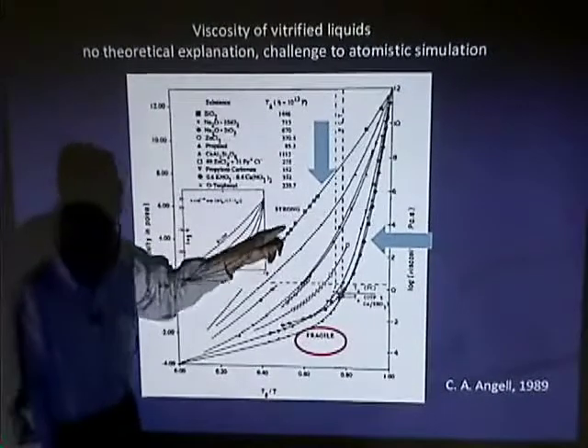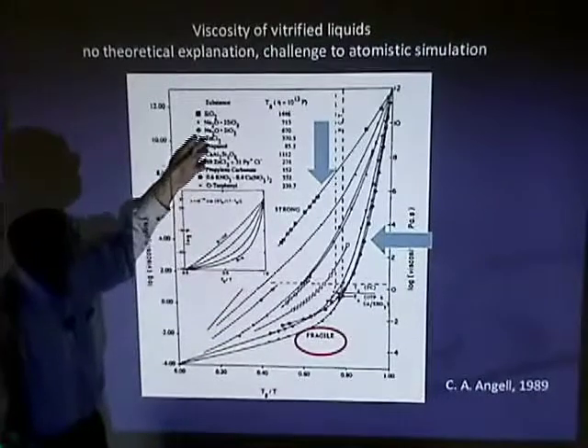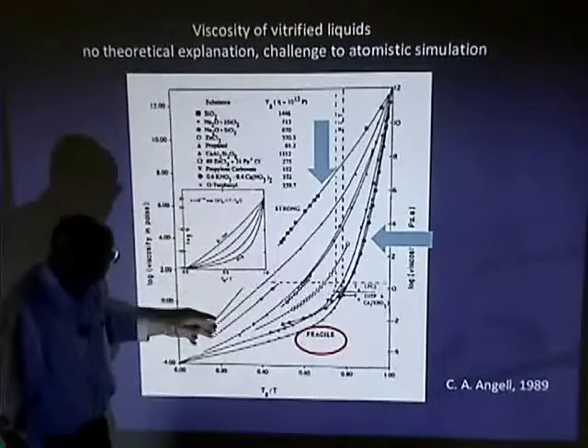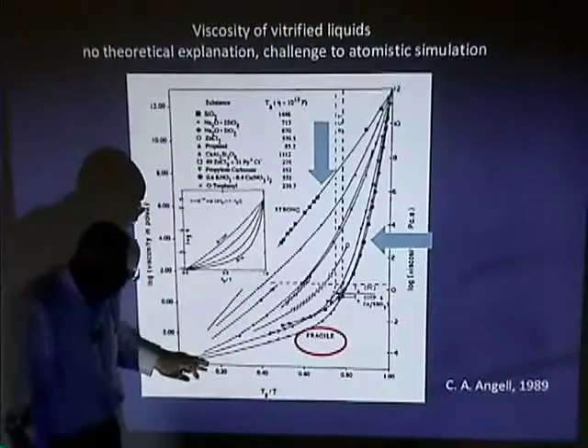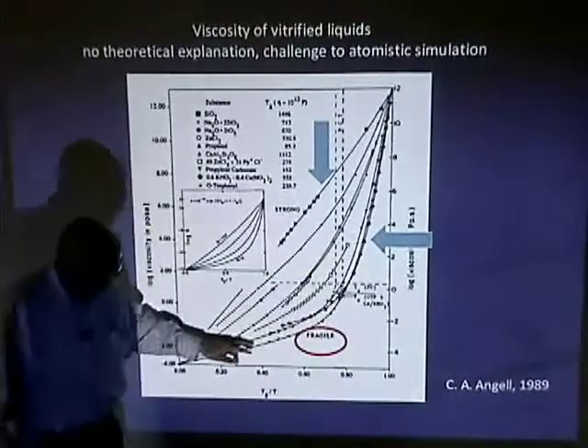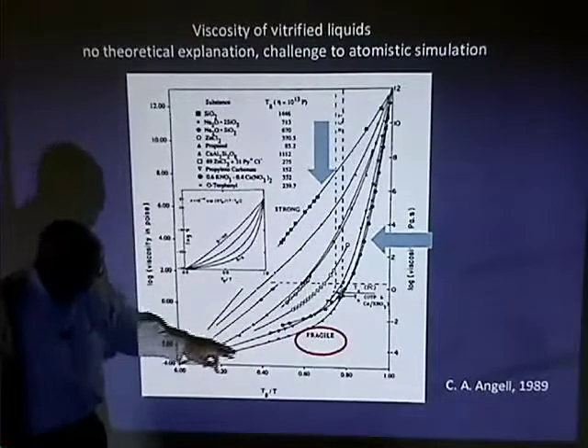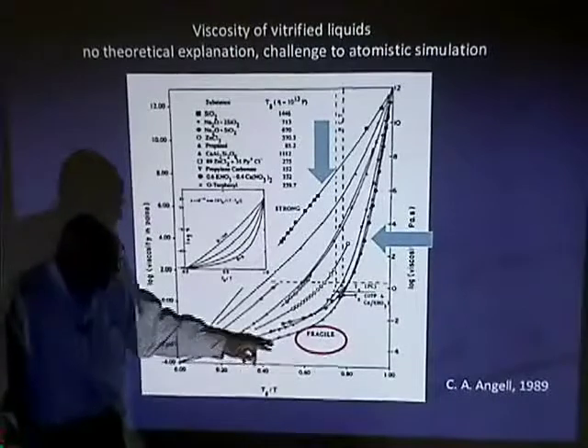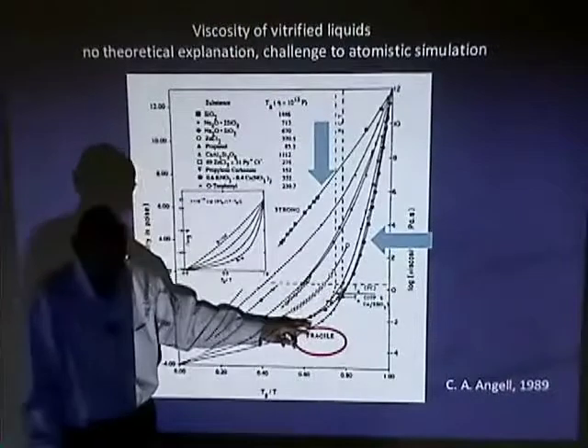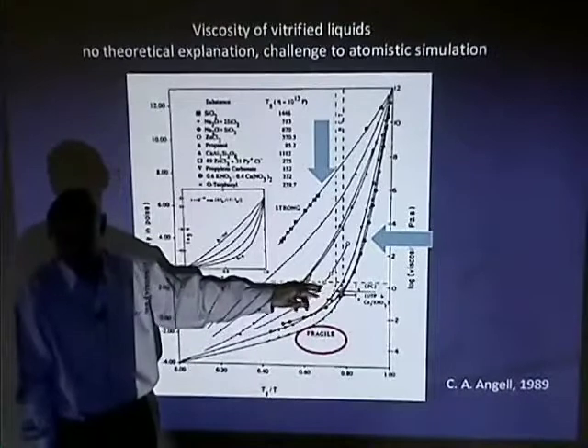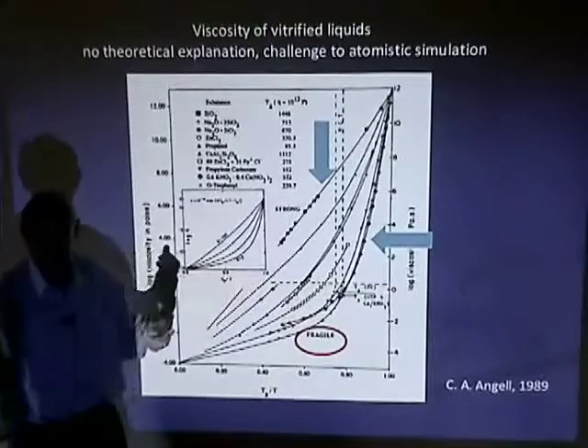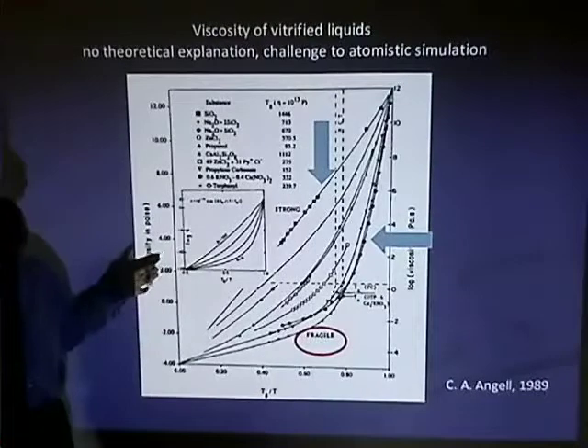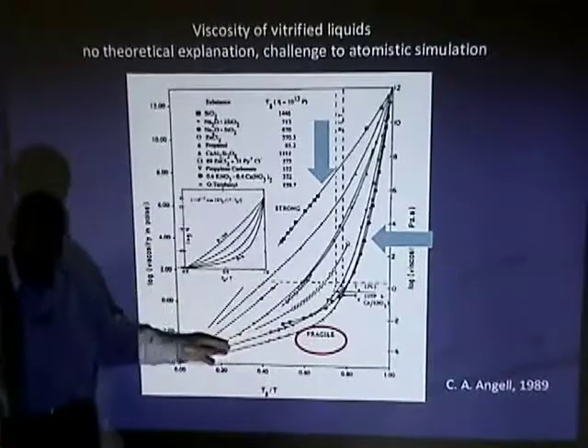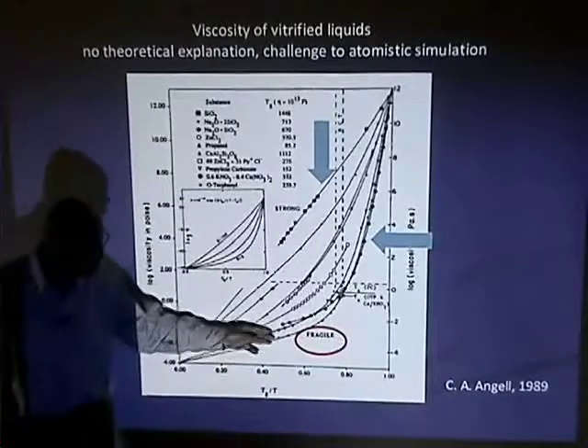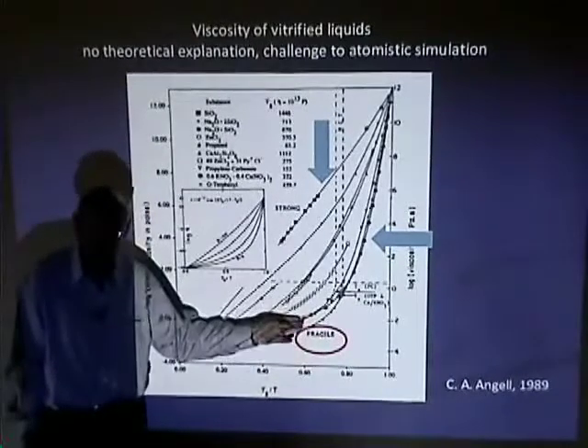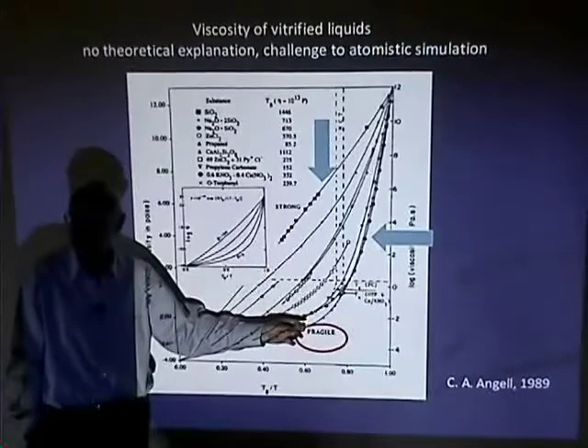All right, take something else. Propanol, propylene, any of these molecules undergo this kind of behavior. You might say this looks like Arrhenius behavior, then it goes into a regime where it's highly non-Arrhenius, super-Arrhenius. If you think in terms of activation energy, the data suggests that the activation energy here is essentially temperature independent.